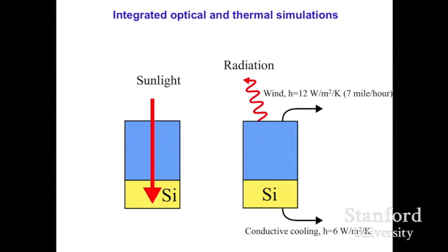Now to really see how this translates into thermal performance, we perform simulation integrating optics and thermal simulation. In this case, we take a structure and then shine sunlight onto it, compute the amount of power that gets deposited into silicon, and this is done by optical simulation. We then do thermal simulation where the solar power is a heat source, and also we put in a convection on the top layer and a conduction on the lower layer in order to simulate some of the other heat loss mechanisms in the solar cell.